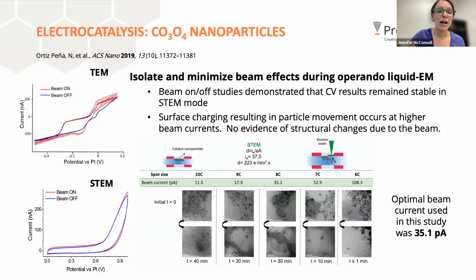So that's usually question number one: how do you know the beam's not affecting the electrochemistry or what you're seeing? She did quite extensive, methodical studies and reported them, and noticed that in TEM mode, she was seeing an effect from the beam and the dose they were using on the electrochemistry. Whereas in STEM mode, where it's a lot easier to control your dose and the area being exposed, she did not see any effects from the beam. So she did her work in STEM mode.